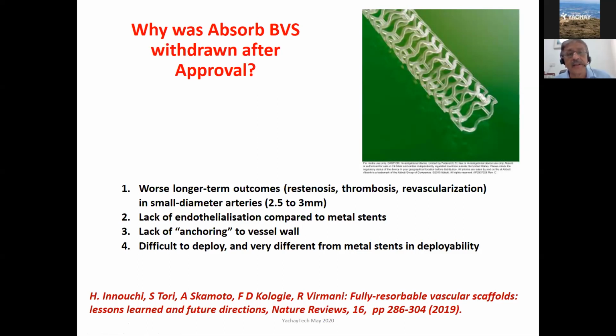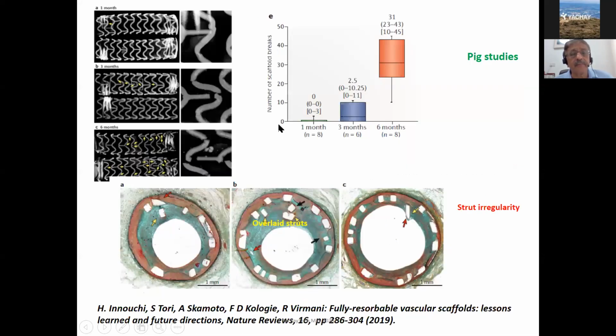So that means that it's not fully touching the vessel wall at all times and can migrate from the site at which it was deployed. And there were lots of problems with deployment and very different in deployability from metal stents. So these have all been covered in a nice paper in Nature Reviews in 2019. And those people also did some pig studies to show problems with these stents.